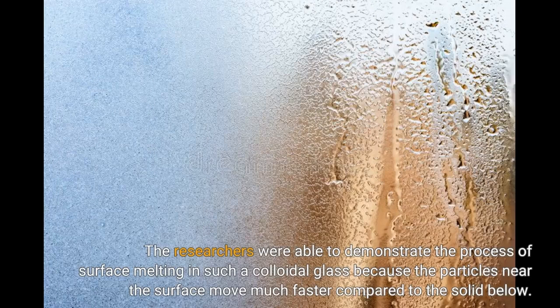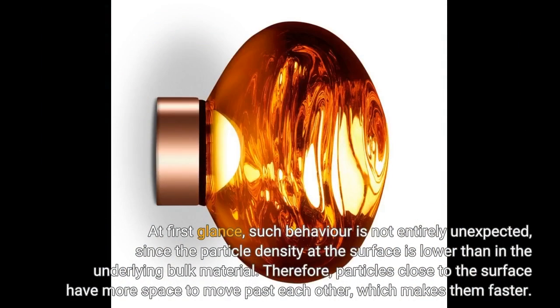The researchers were able to demonstrate the process of surface melting in such a colloidal glass because the particles near the surface move much faster compared to the solid below. At first glance, such behavior is not entirely unexpected, since the particle density at the surface is lower than in the underlying bulk material. Therefore, particles close to the surface have more space to move past each other, which makes them faster.